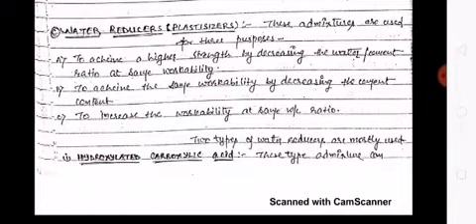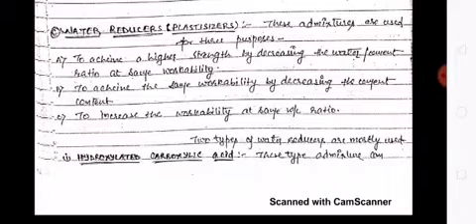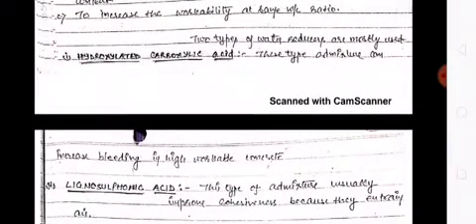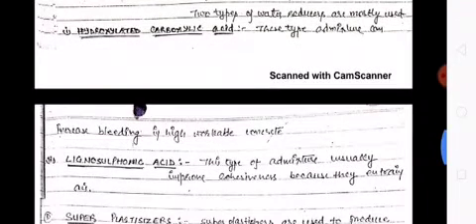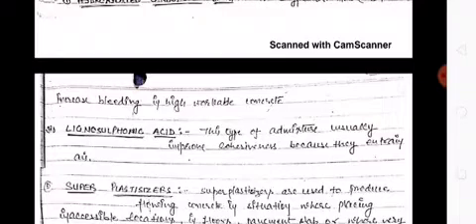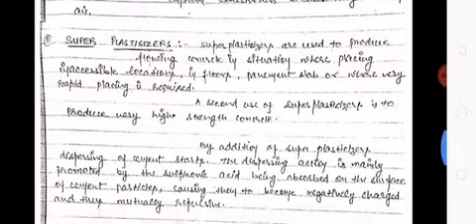Water reducers and plasticizers are used for three purposes: first, to achieve high strength by decreasing the water-cement ratio at the same workability; second, to achieve the same workability by decreasing the cement content; third, to increase workability at the same water-cement ratio. Two types of water reducers are mostly used: first, hydroxylated carboxylic acid, which can increase bleeding in high-workability concrete; second, lignosulfonic acid, which usually improves cohesiveness because it entrains air.